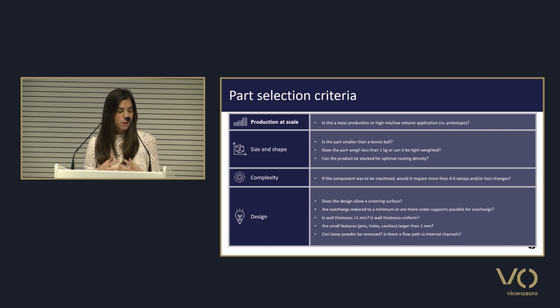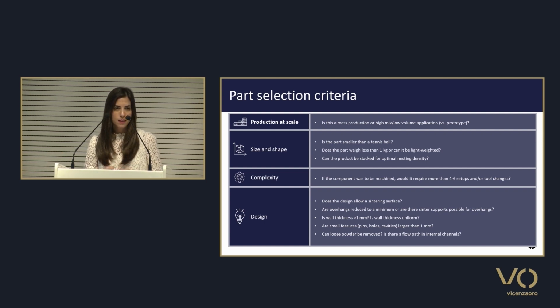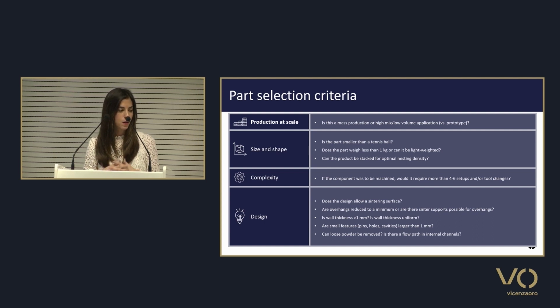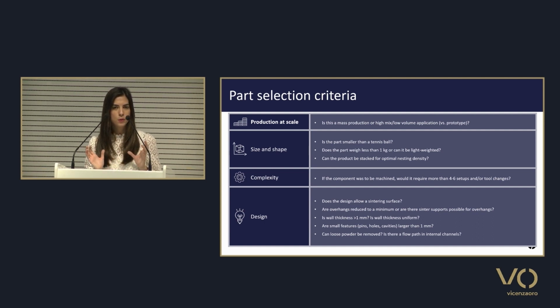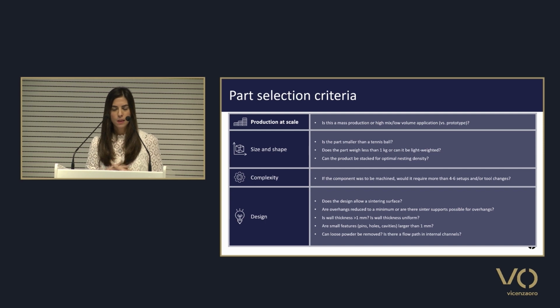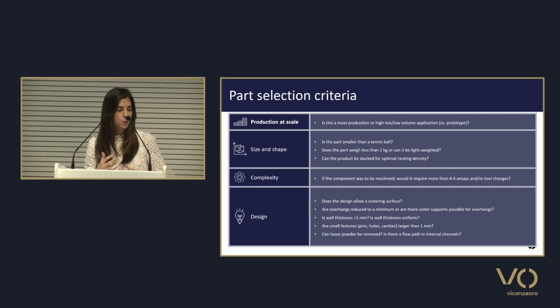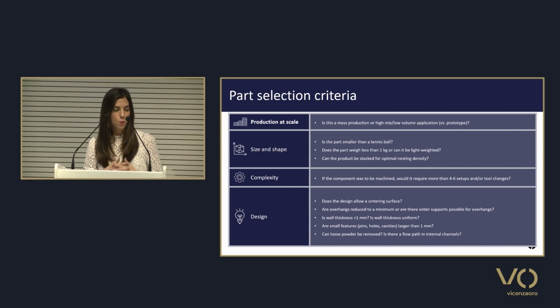When talking about wall thicknesses, the minimum recommended wall thickness is around 1 millimeter. We can go lower than that in specific cases, but the minimum recommended is around 1 millimeter, and it's important to have uniform wall thickness as well, and smooth transitions. This comes from the sintering as well, otherwise you will see distortions that are not wished. And finally, looking at small features, pins, holes, cavities, and so on, the recommended size is also around 1 millimeter.